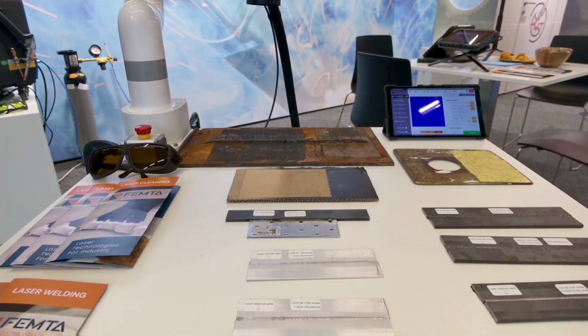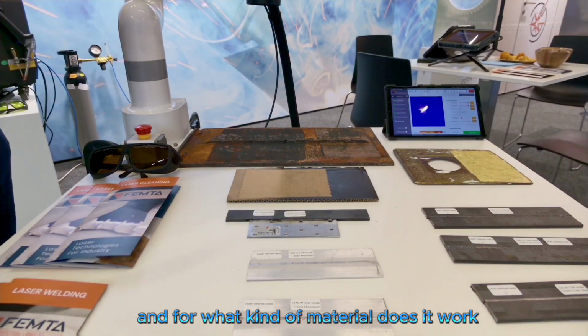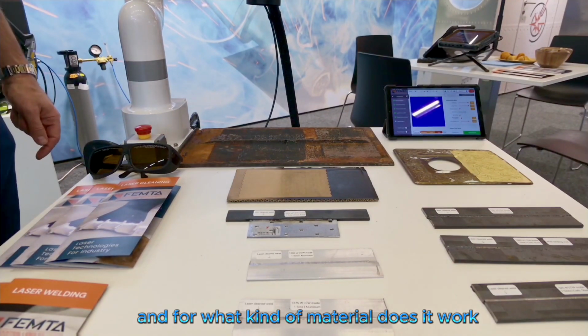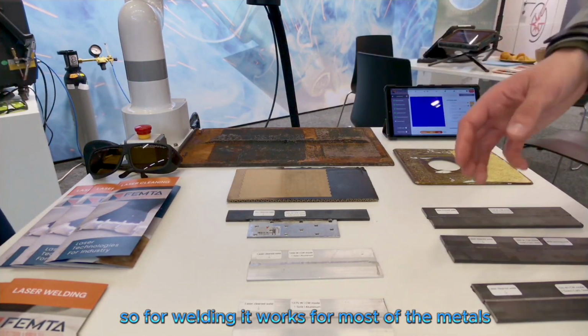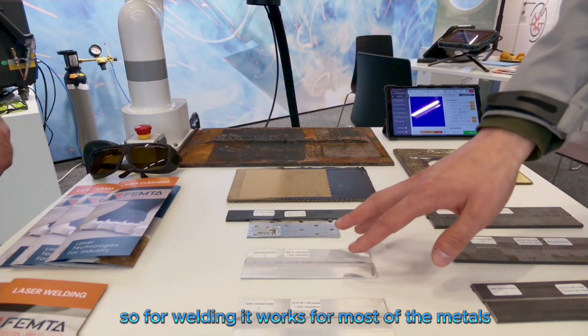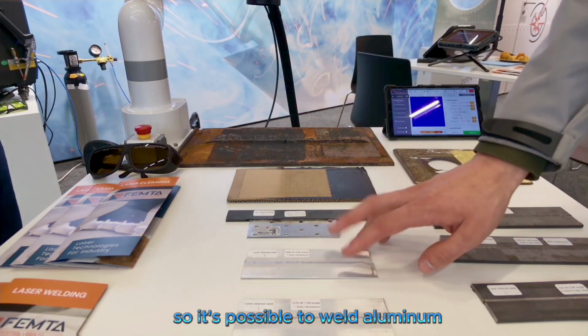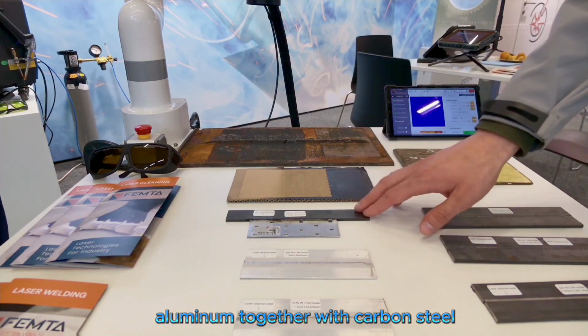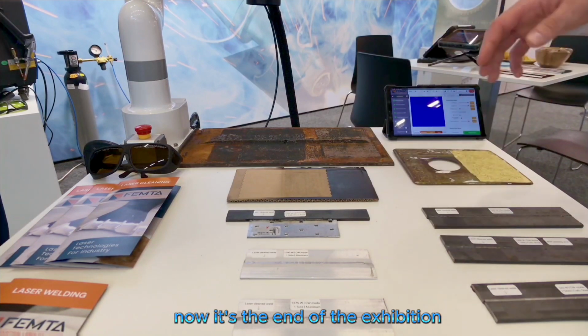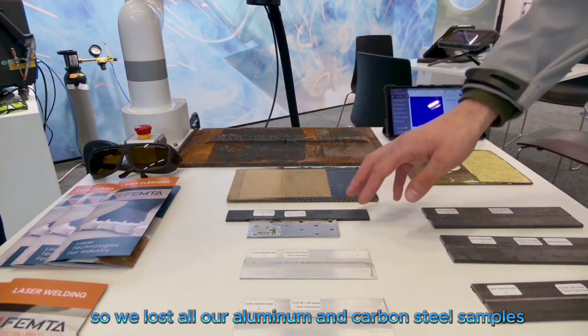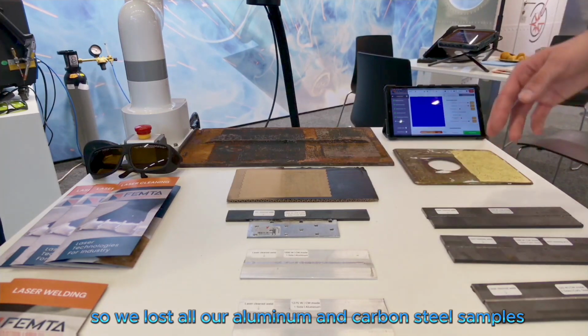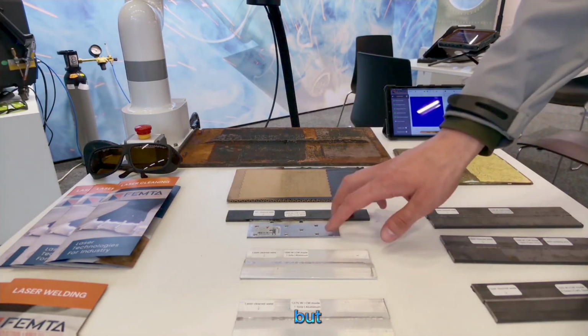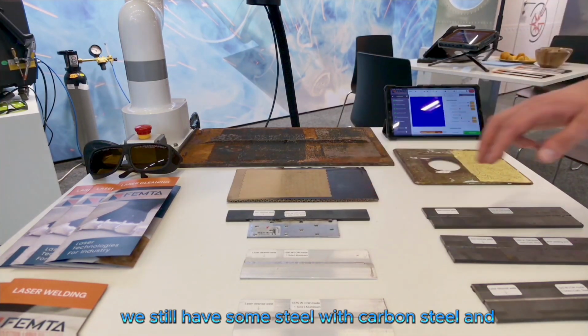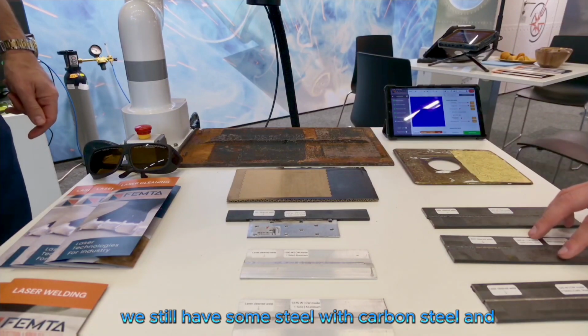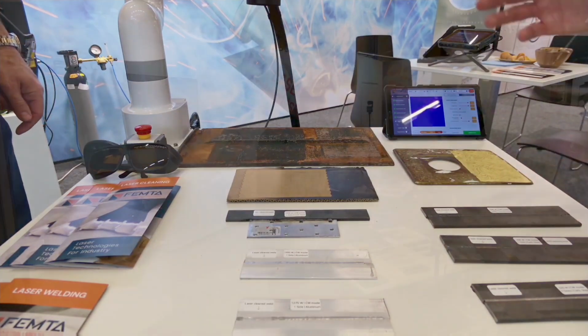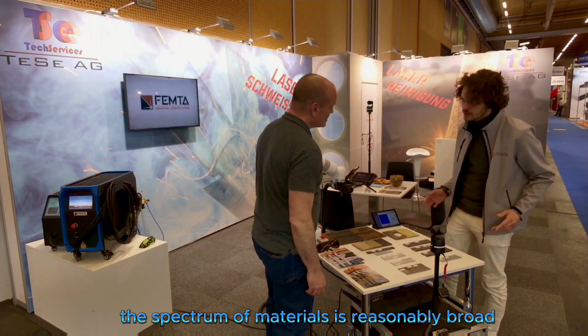And for which kind of material does it work? So for welding, it works for most of the metals. It's possible to weld aluminum together with carbon steel. Now it's the end of the exhibition, so we lost all our aluminum and carbon steel samples, but we still have some steel with carbon steel. And the spectrum of materials is reasonably broad.